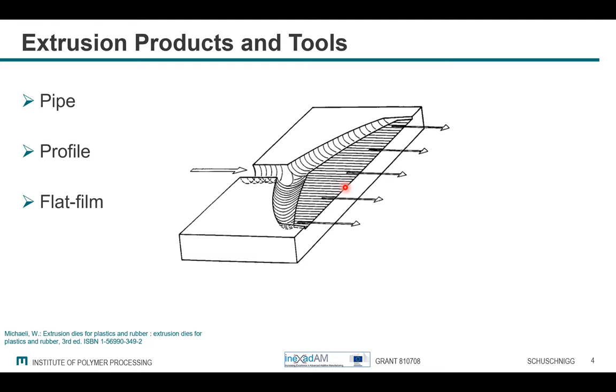And there is an analytical method for a certain type of coat hanger dies, but the problem is that they have corners inside where the residence time will be too high, and then the polymer, which is in the hot die, starts to degrade. So therefore, we need for each polymer, for each processing parameter, a certain optimized die.